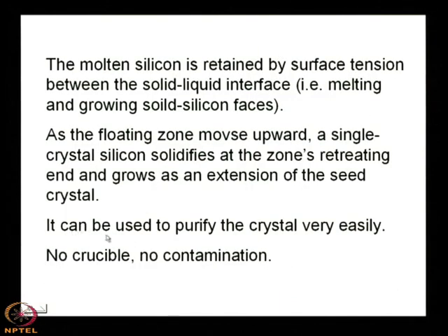It can be used to purify the crystal very easily, no crucible and no contamination. That is the most important advantage of the float zone technique, that because of no crucible, no contamination takes place, and so it can be purified very easily. Why do we use this term purification? We use this term because when crystallization takes place, generally all bulk crystal is made using the melt growth process. That means, first the material is melted and then it is pulled using a seed crystal.